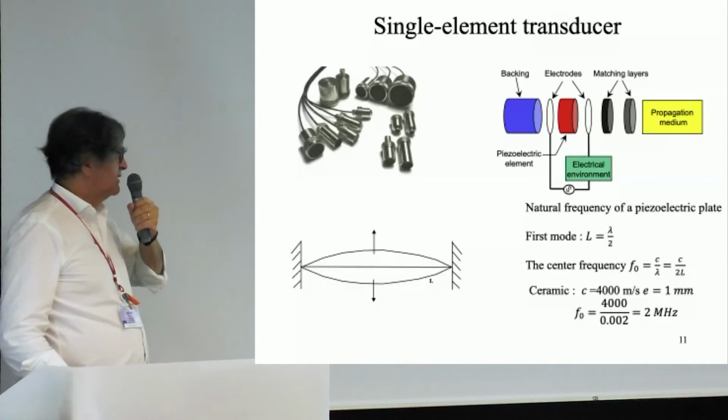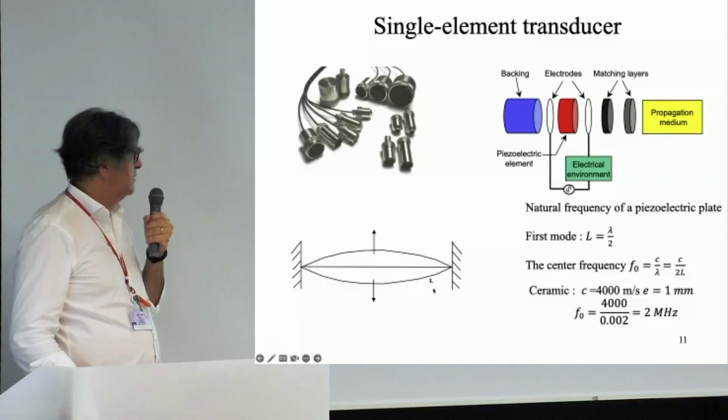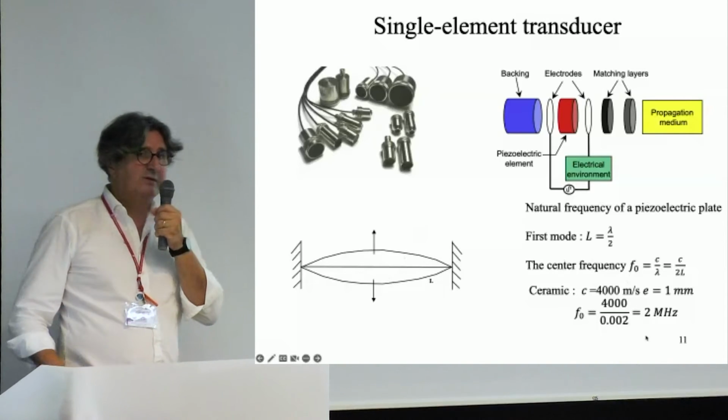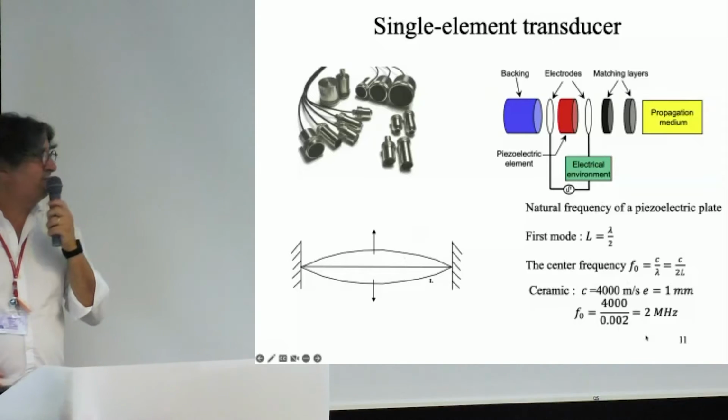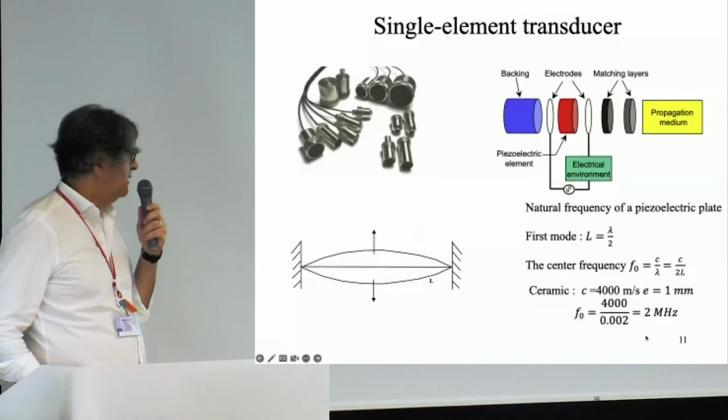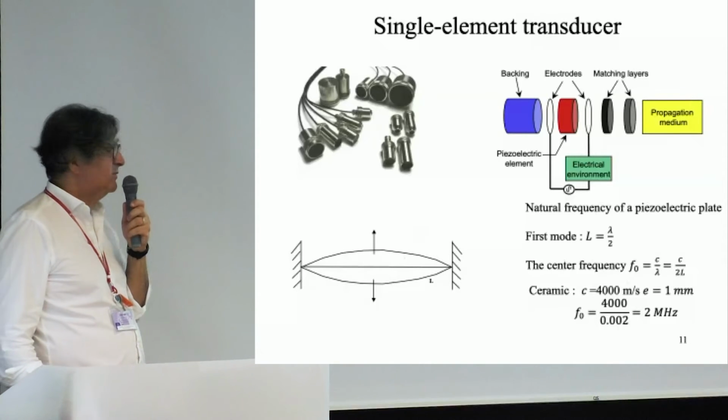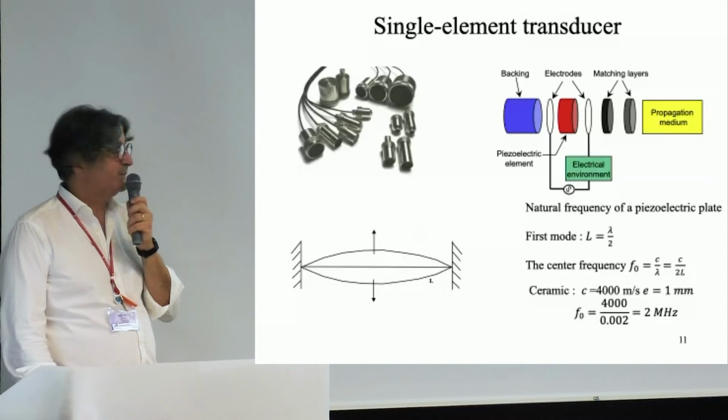I will not explain the resonance mode again, but just to say that typically for a 1 millimeter thick ceramic, we have a 2 megahertz resonance.